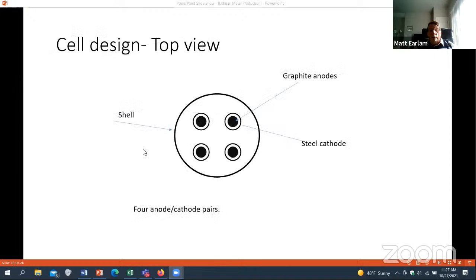So if you look at the current cell designs, what they basically are: 4 anode cathode pairs in a tub, and each one has a cathode in the center, so it's a center ring, and then an anode in each one, and they put current through it, and they generate lithium metal that floats on this surface. Hopefully they've constructed the gas lift action so that it gets directed towards the front, so the operator can collect the lithium metal in a ladle, which is what he does.